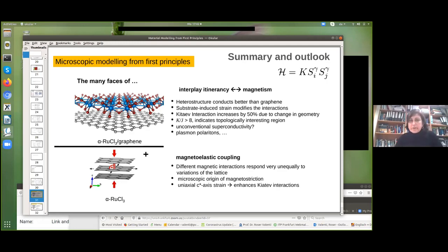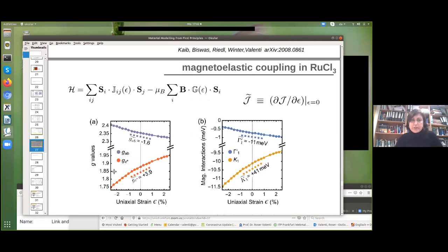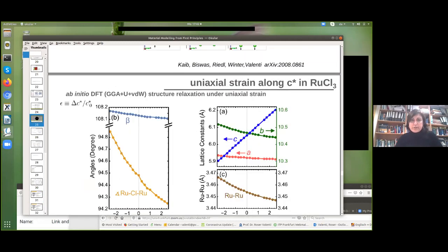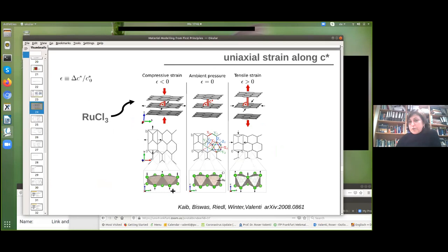And this probably one can see in this picture here, where you see that the A and B direction get differently affected, or you can even see it here when I plot. There is a different effect of the A and B direction to this uniaxial strain. So it's a different effect on the lattice, on the ruthenium trichloride.